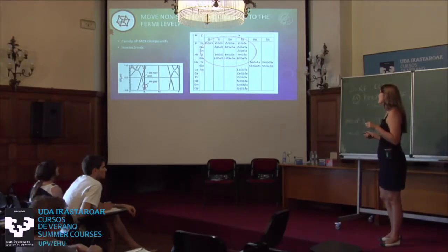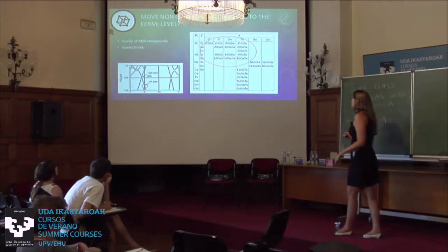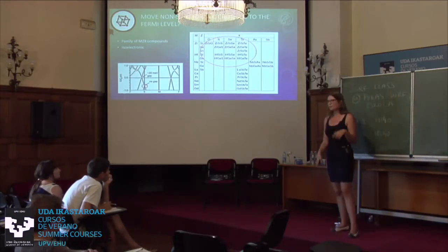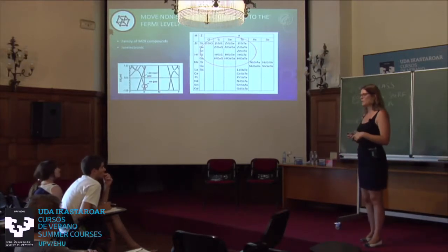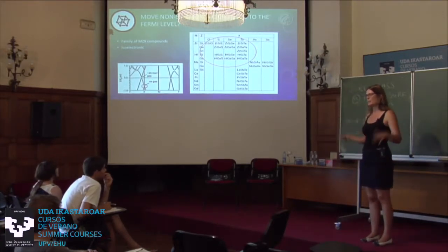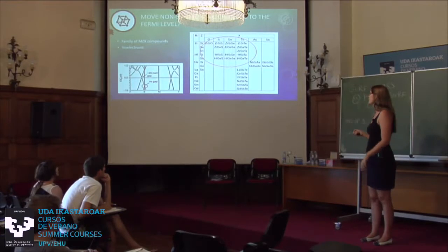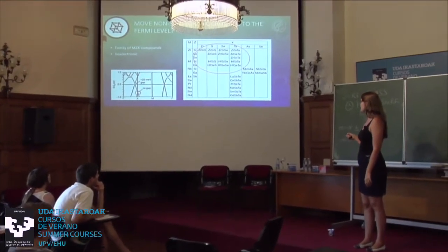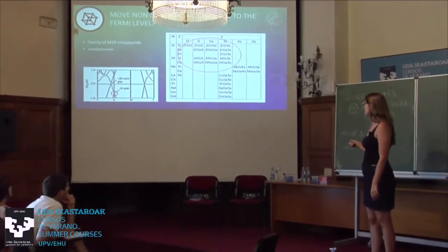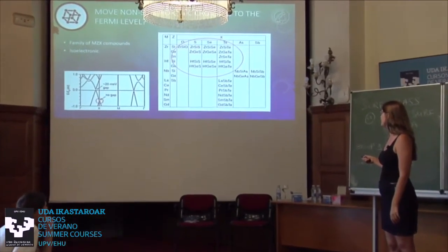So I thought maybe we use something called chemical pressure, which is actually a very common concept in chemistry, where you substitute an element with a different element which has a larger size, right? We were talking about the radii and the sizes before. And because this element is larger, it strains the whole material. So I wondered, okay, maybe we look at those compounds first here and see, can you substitute sulfur with tellurium here.